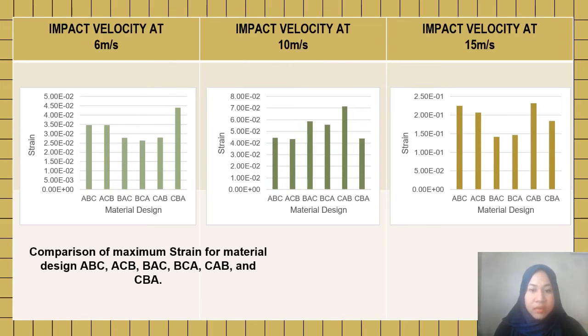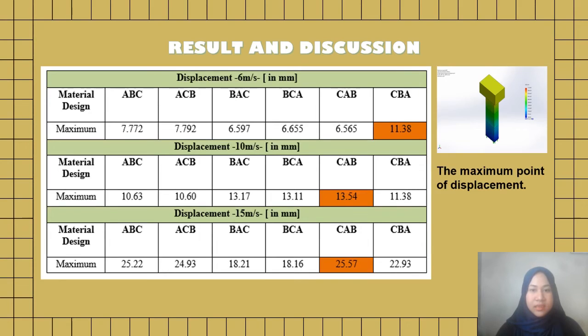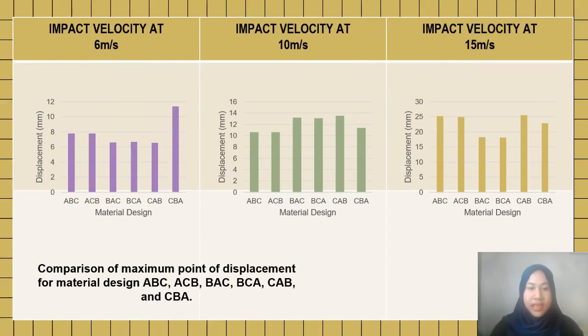Based on this finding, the study concluded that the highest value of strain occurred on combination layers of material designs that included a component of material C. After that, this is the result of the maximum point of displacement for every impact velocity. As you can see on the graph, the highest displacement for impact velocity at 6 meters per second is material design CBA, which is 11.38 mm. It is slightly higher than the other material designs. For impact velocity at 10 meters per second, material design CAB produced the highest displacement, which is 13.54 mm, while at 15 meters per second it is material design CAB with 25.57 mm.